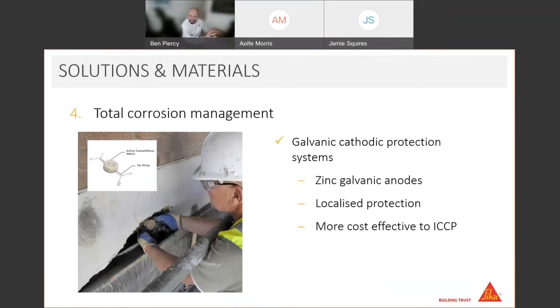If you were guaranteeing just the actual repair that's been done there, these anodes would stop what's called incipient anode corrosion. The fresh, high alkali concrete that's been placed into that repair, if there wasn't the anode, would actually encourage corrosion around the repair in years to come, and not long. It could be two, three to five years after. What the anode does is stop that incipient anode corrosion occurring around it, and that's how they work, and that's how we're able to offer this total corrosion management guarantee. We have different types of anodes available, and we're able to specify a 10, 15 or 20 year material guarantee.